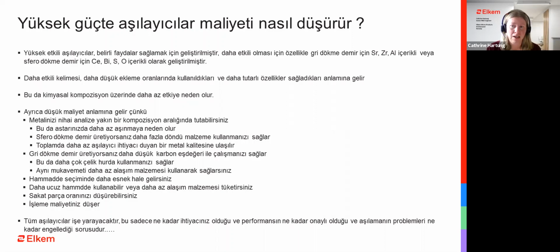More effective means that they allow for use of lower addition and provide more consistent properties. This again leads to less impact on chemical composition. It is more of the composition that you have put in the furnace, so the more of the silicon that you have put in the furnace, the more you can save on alloying addition. This in turn means lower cost because you can run your base iron closer to final iron composition, which leads to lower wear on your lining. If you run higher silicon in the furnace, your wear on the lining is less.